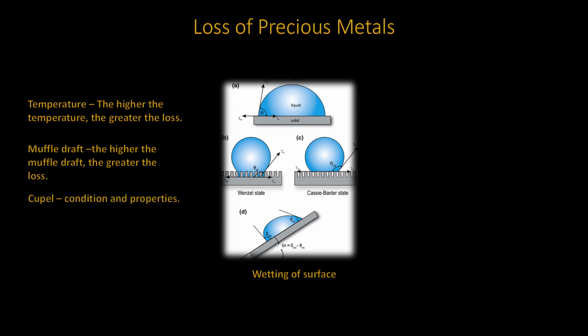Poor quality cupels would either be too porous or too dense. Losses will occur as material may be absorbed. If too dense, cupellation time is increased. Both conditions equate to losses. Any cupel on inspection prior to use, if it is badly pressed or too porous in appearance, should not be used. Discard it. Silver is more readily oxidized than gold.